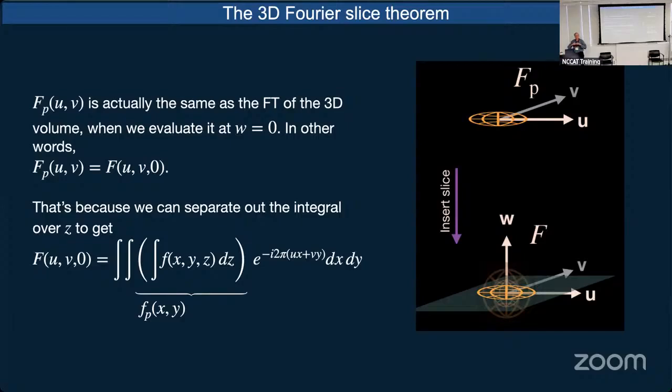For people doing electron tomography where there is a big missing wedge in Fourier space, you can tweak the algebraic reconstruction to handle that the way you want. The Fourier slice theorem is faster, but it assumes you have equal coverage in the entire Fourier space.